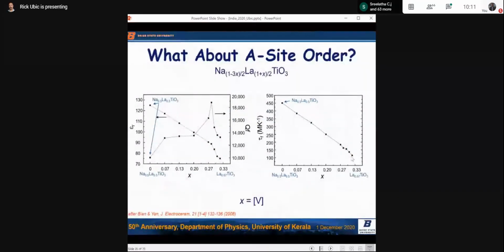Now, what about A-site ordering? For the A-site, we first started doing this with sodium lanthanum titanate, which was an interesting microwave material, about 12 years ago, I guess now. This was first published. It's because the microwave data looked promising. You had kind of large permittivities, which looked good. And since you have such a large permittivity, you have lots of room to engineer this. If you have to sacrifice some permittivity, you had it there to sacrifice. You had kind of large quality factors, which means you have low losses. The temperature coefficient looked a bit large, but it was also coming down.